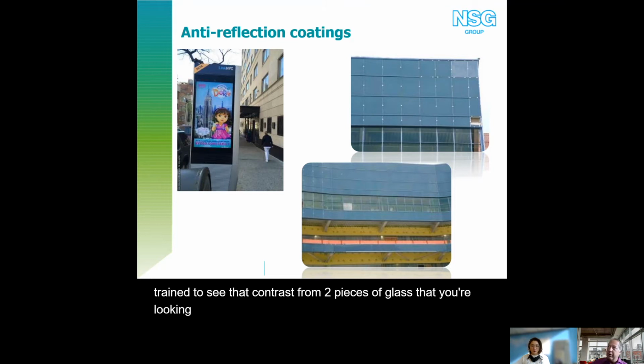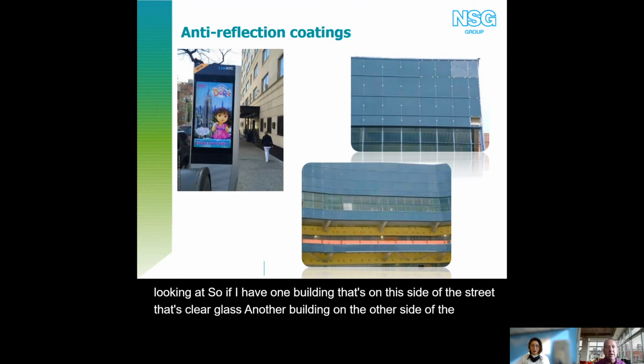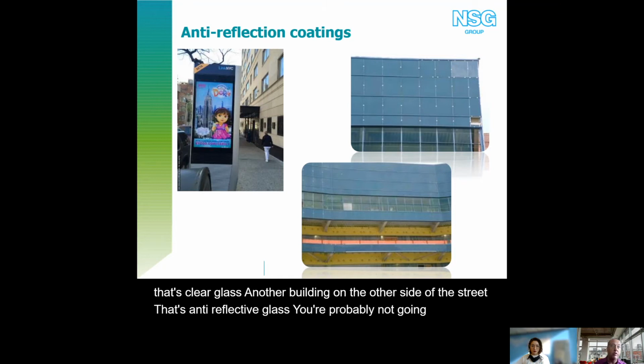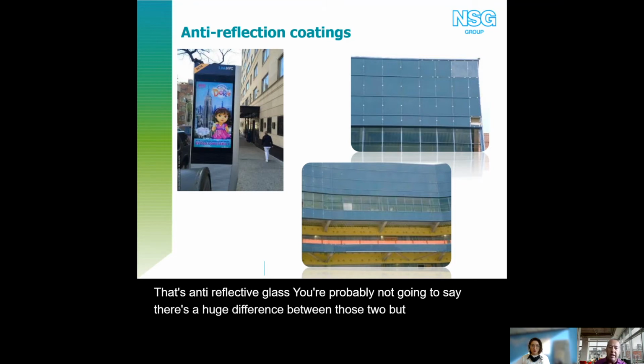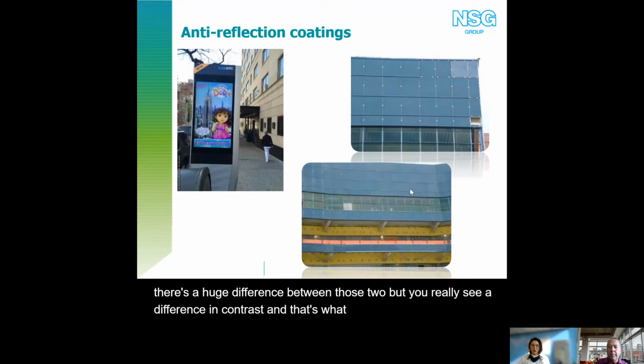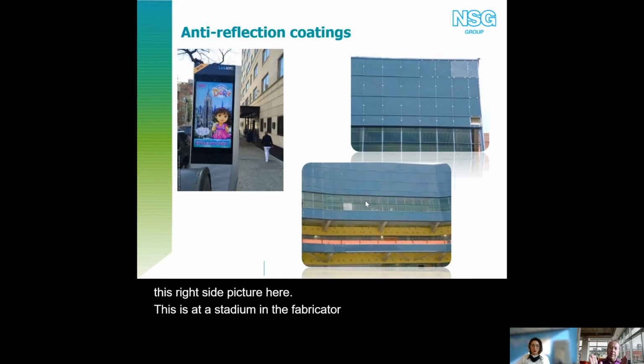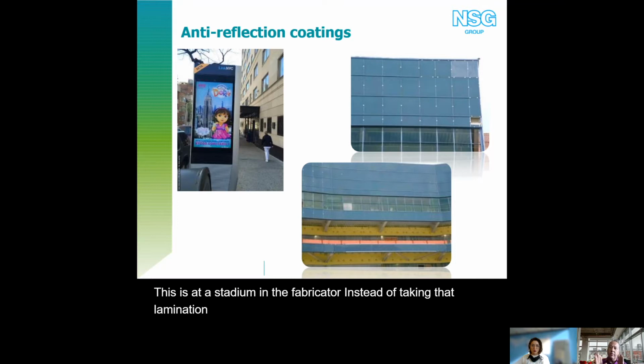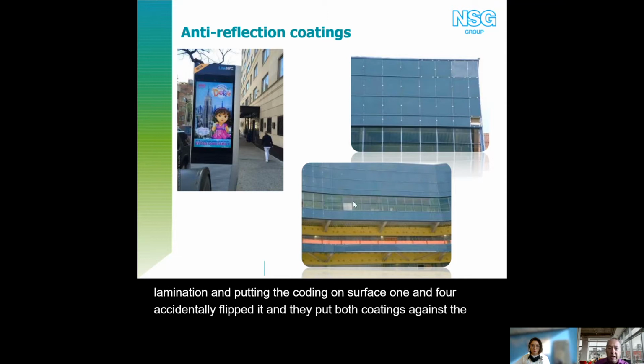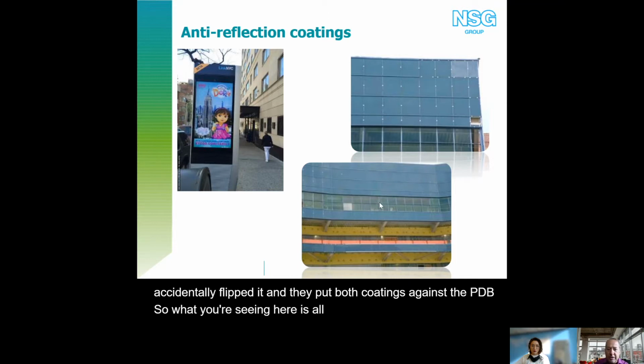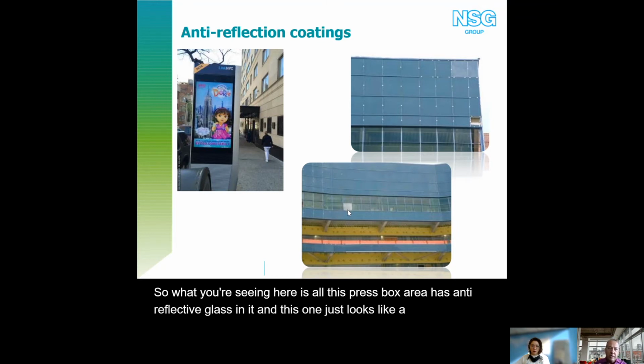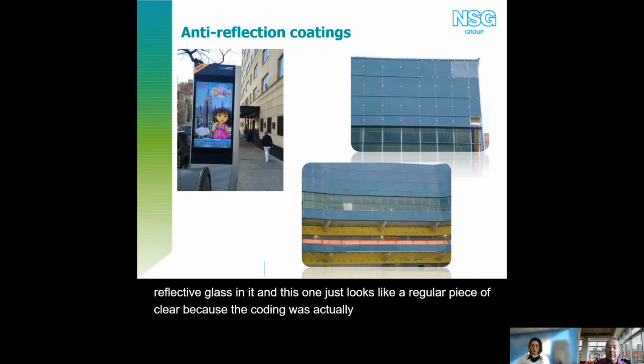So if I have one building on this side of the street that's clear glass, and another building on the other side of the street that's anti-reflective glass, you're probably not going to say, oh, there's a huge difference between those two. But you really see a difference in contrast. And that's what I'm showing you on this right side picture here. This is at a stadium, and the fabricator, instead of putting the coating on surface 1 and 4 of the lamination, accidentally flipped it and put both coatings against the PVB. So what you're seeing here is all this press box area has anti-reflective glass in it. And this one just looks like a regular piece of clear because the coating was actually against the PVB. So you don't get that anti-reflective benefit.